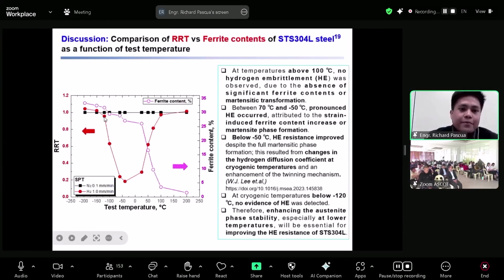This is due to the changes of hydrogen diffusion rate or enhancement of twinning mechanism at cryogenic temperature. And when it reaches below negative 120 degrees Celsius, it does not give any hydrogen embrittlement effects in the material. Therefore, to improve or enhance the HE resistance of this material, it is important to improve its austenitic phase stability, particularly at lower temperature, from 70 degrees Celsius to negative 120 degrees Celsius.